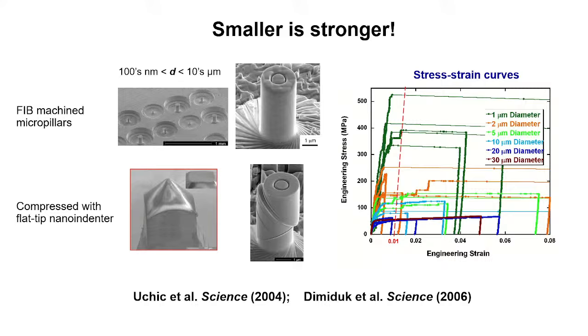But what Mike Uchic and Dennis Dimiduk, who were at that time at the Air Force Research Labs, showed was that if you make pillars of different sizes, and they made these pillars by nano FIBbing, so these are different size pillars that they FIBbed out of a large single crystal. These were made out of nickel, and then you deform it. You take this pillar and you deform it using a flat top nano indenter, not a conical or a Berkovich indenter, but an indenter that had a flat top machined on it, and you push down on it, and it behaves like a single crystal.